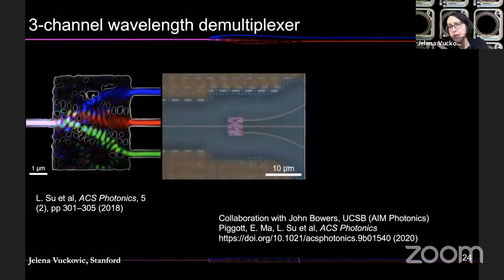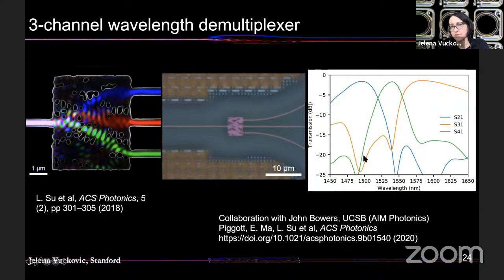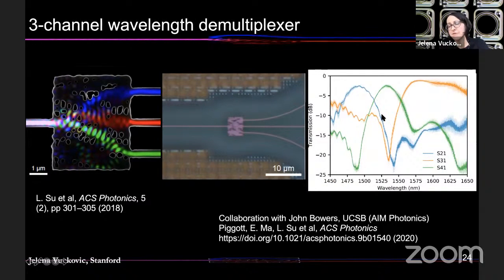So for foundries, which primarily work with silicon, we've also spent the last couple of years showing that you can actually do this in a foundry. So for example, the 3-channel wavelength splitter we fabricated at Stanford and demonstrated. Here is the same splitter made in a commercial foundry. Here is the theoretically predicted behavior, transmission into 3 different channels, and here is the measured behavior for many devices on the chip. Again, they're robust to fabrication errors, and small degradation relative to theoretically predicted behavior comes from the fact that we didn't really know precisely minimum feature sizes in a foundry. They were around 100 nanometers, and we designed this for minimum feature size of 80 nanometers.